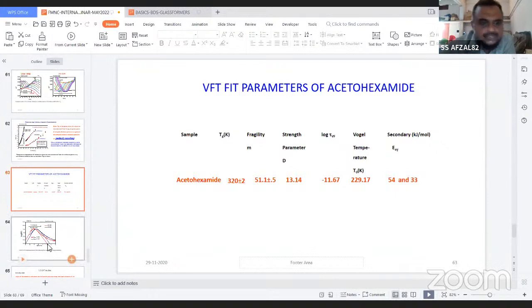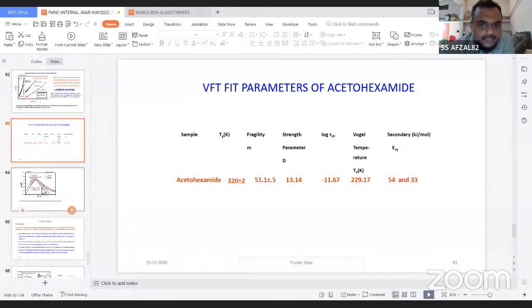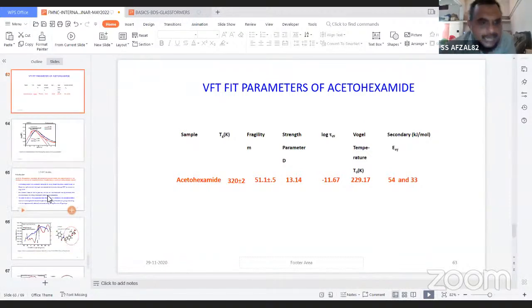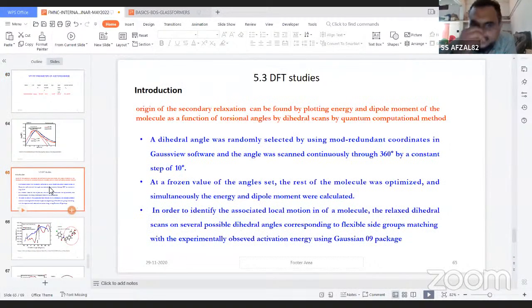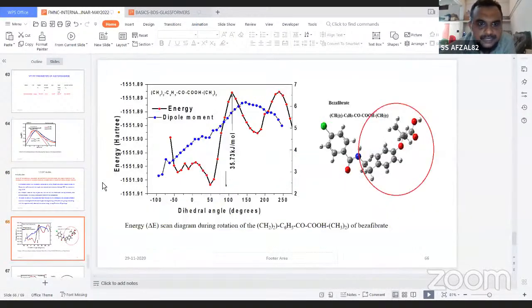There are many things to show. Because of the time limit, I am showing this. And one more thing is by the DFT method, using the Gaussian software, we have conducted a theoretical study and plotted this graph. That is, we rotated a particular side chain of the molecule, and then we drew the energy scan diagram, and this energy corresponds to the activation energy of the secondary relaxation found from this Arrhenius diagram. So this is a correspondence.